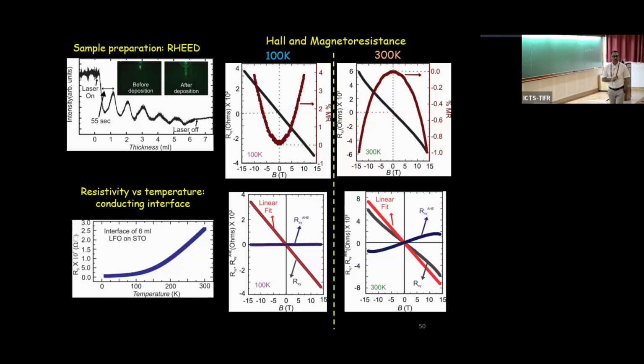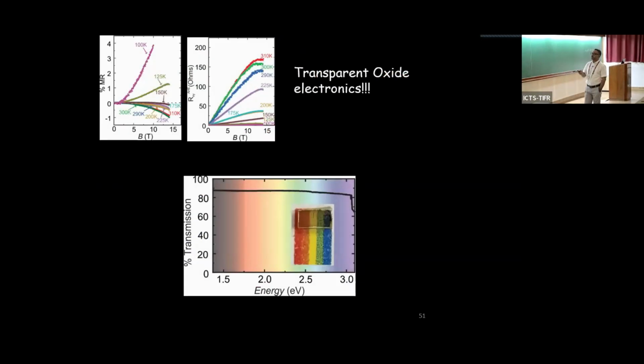Usually this positive magnetoresistance we observe at the lower temperature, and at high temperature you see a negative magnetoresistance. And at the high temperature you see a non-linear Hall. When you subtract this linear fit, you see this anomalous Hall part coming in the system. So we made a systematic temperature dependent measurement, and we can see that from 100 Kelvin up to around 150 Kelvin or below, it is a positive magnetoresistance, and above that it is negative magnetoresistance. And this anomalous Hall also starts above 100 Kelvin, and it remains even up to room temperature.